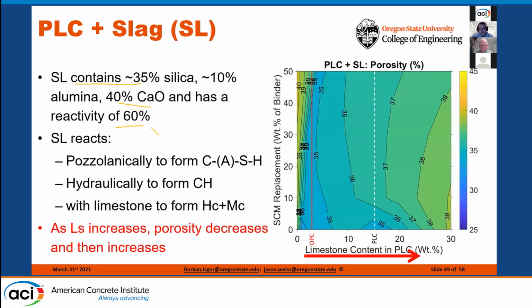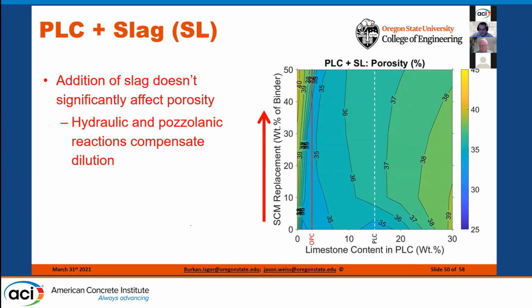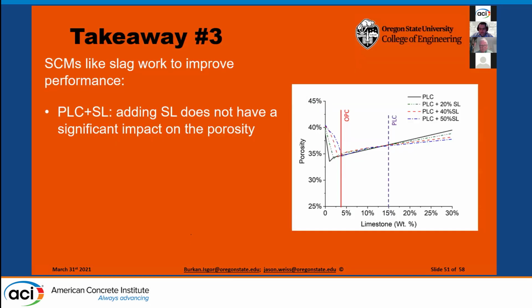And what we can now start to see is, again, as we add limestone, the porosity decreases, and then it goes slightly back up as we increase to higher and higher levels. But in all of these regions, the porosity is actually lower than it was for the ordinary system on its own. And while the slag doesn't significantly affect the porosity, it does start to change how those pore phases are distributed, and it does start to change some of the reaction products, making them much more stable as a function of time. So again, our takeaway here is slag really can help to improve performance.